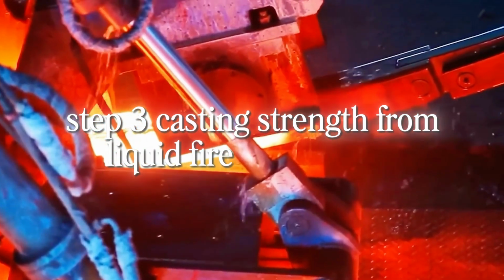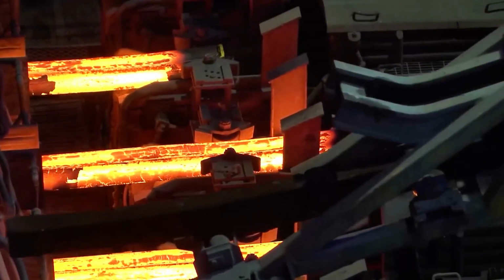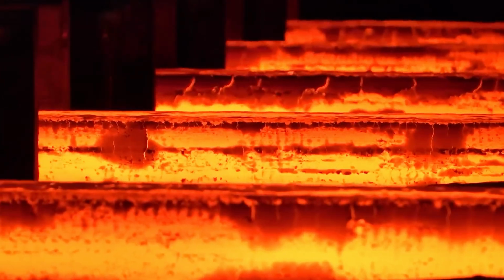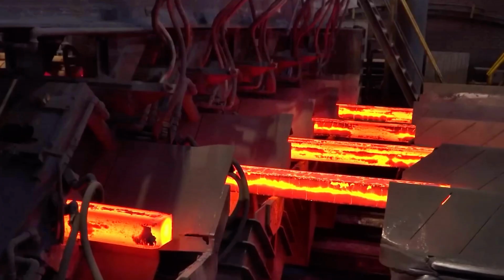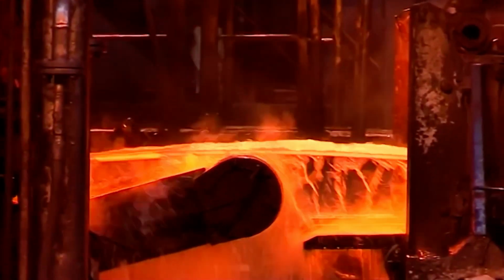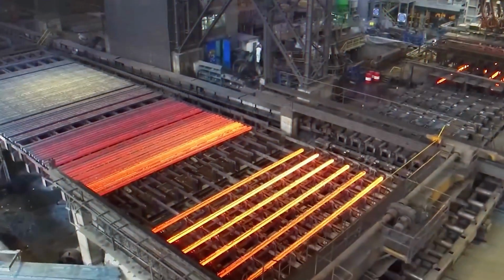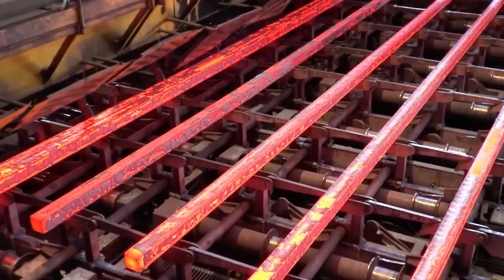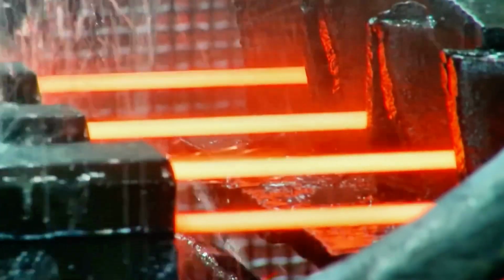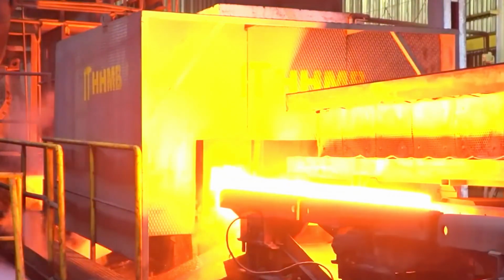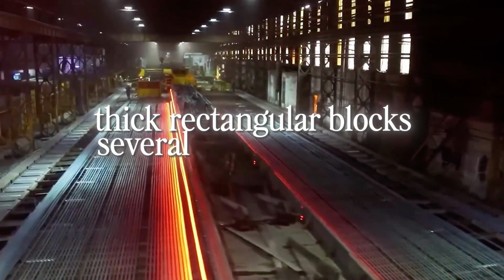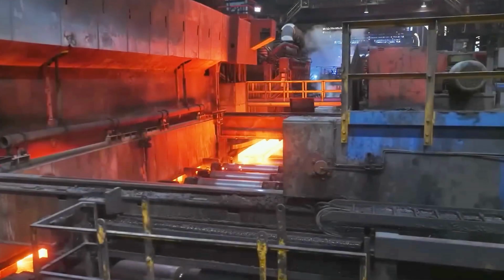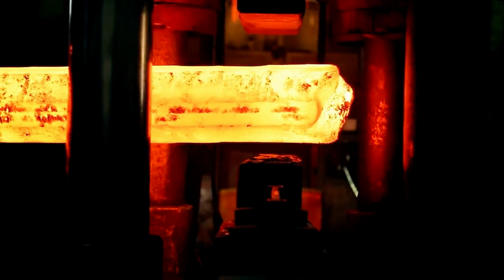From liquid fire to solid form. Once the molten steel is perfected, it's time to give it shape. The liquid is poured through special copper molds in a process called continuous casting. These molds are cooled by powerful water jets, freezing the steel's outer layer in seconds while the inside remains molten. Slowly, the metal solidifies from the outside in, emerging as long, glowing billets, thick rectangular blocks several meters in length. Each billet moves directly from casting to rolling while it's still red hot, wasting no time and no heat.